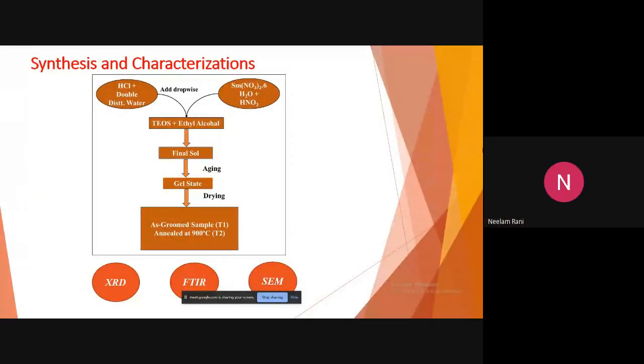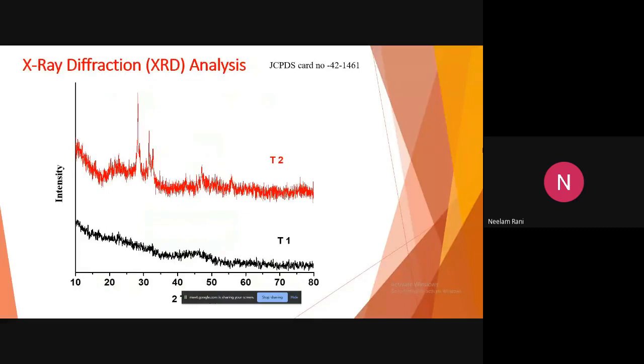Okay, sir. Thanks. This is the synthesis and characterization technique, the synthesis flowchart, and this is the XRD of my prepared sample. Here T1 is defined as the as-prepared sample at room temperature, and T2 is annealed at 900 degrees Celsius. There are some humps in the range of 22 to 30 and 42 to 50. This defines the silica humps.